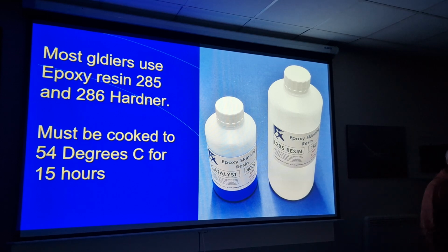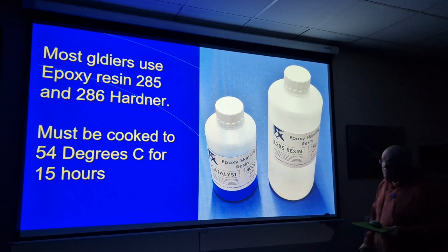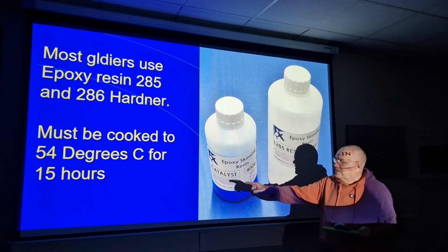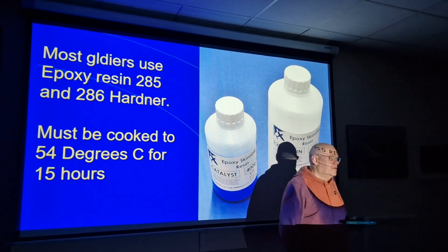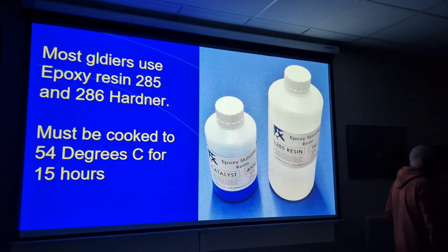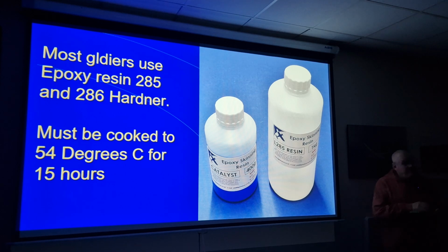Let's take it to 40 degrees. The whole lot will go soft and floppy. It's no good to us, because it has to be good for at least the temperature. So the law says, since the mid-1960s, gliders must tolerate a temperature of 54 degrees centigrade. So after every glass fibre glider is built, or wooden glider for that matter, they bake the whole glider at 54 degrees for 15 hours. That's the law.